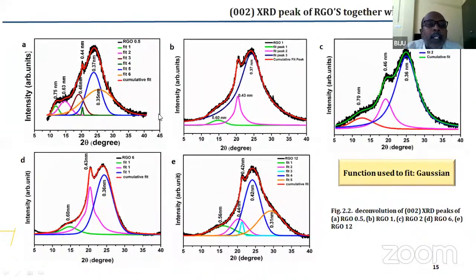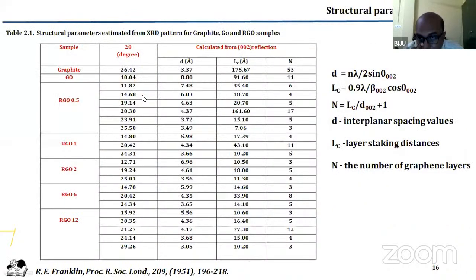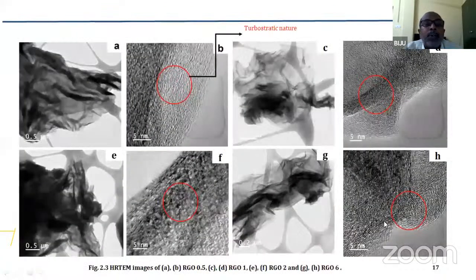So we have deconvoluted the XRD, then obtained the different d values present, and also estimated the number of layers with each d value. All these are summarized. These details you can find from literature, and these are the d values as well as the number of layers with each d value that we have obtained for the RGO samples. Let us concentrate on RGO 0.5, which has different d values and also different number of layers for each. That is the sample that we are going to analyze.